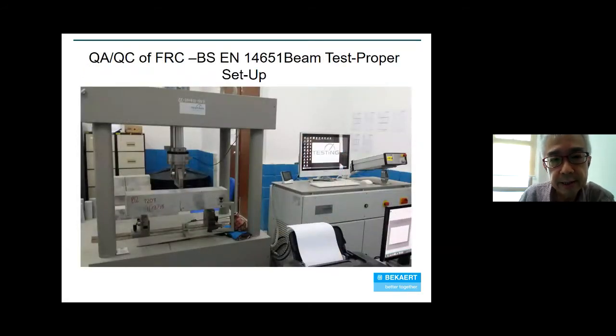The second test that we should do on a daily basis is a beam test called BS EN 14651, and this is the setup for the beam test. It's a beam with a notch at the center, and underneath the notch is a crack mouth opening displacement transducer, and it measures the opening of the crack mouth. So from this test, you will be able to get, next slide please,